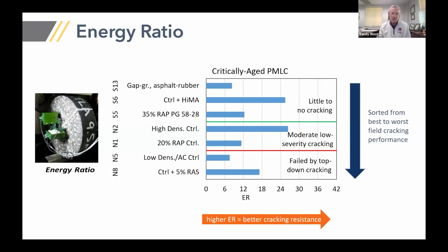So energy ratio, a better or higher number was considered to be better by this research, by the previous research. But what we can see from this chart is it did not rank these mixes correctly. Some mixes with low energy ratio did really well, and some mixes with reasonably high energy ratios failed. So it did not show us the correct ranking.